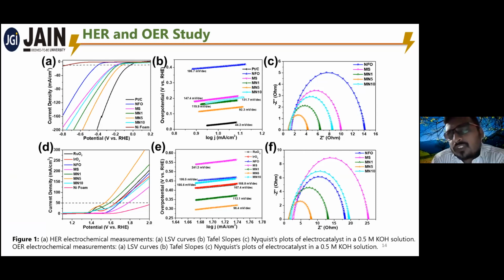From the Tafel slope of the HER, the lower value for the Mn5 catalyst represents higher kinetics, so the reaction is also faster compared to the bare materials. Electrochemical impedance spectroscopy gives us the information that the charge transfer resistance of the nanocomposite is very low compared to the bare materials, and the optimized structure of Mn5 shows the best results.